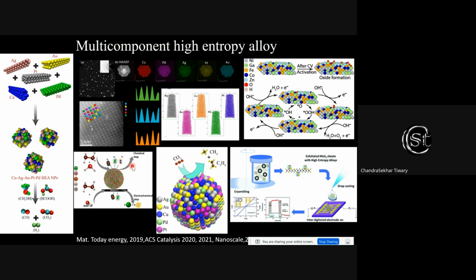And what we observe in our experiments over the last 3-4 years is that, for example, if you have individual bulk copper versus copper in high entropy, the chemical activity is completely different. As a result, you can have a nanoparticle consisting of copper in a high entropy state, which can behave completely differently and do a lot of reactions which were not possible using bulk or nano copper. Similarly, we have made structural metals into a high entropy form, like nickel, gallium, iron, and so on, which do hydrogen evolution or oxygen evolution, and we also utilize them for multiple sensing and so on.